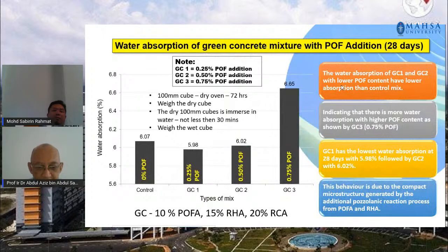Water absorption. Again, this is another test that we did for the green concrete mix. The one with the highest amount of palm oil fiber shows the highest amount of water absorption, so this is not a good indicator. Whereas the least amount of palm oil fiber shows the least amount of water absorption. This seems acceptable, being very near to 0% fiber, at 6.07 and 5.98 of water absorption.